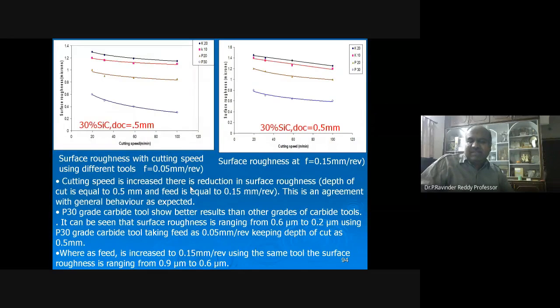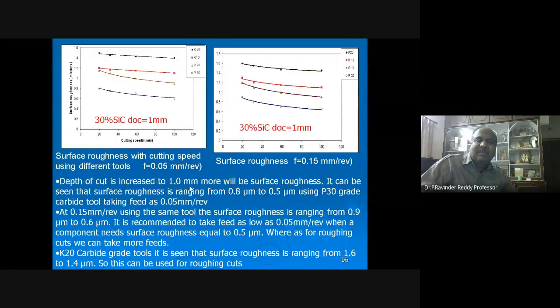So we have calculated at different feed rates, keeping feed rate constant and depth of cut constant; all the parameters have been studied. As the depth of cut is increased to 1 mm, the surface roughness will be higher. It can be seen that the surface roughness ranges from 0.8 microns to 0.5 microns using the P30 grade carbide tool. At 0.15 mm per revolution using the same tool, the surface roughness ranges from 0.9 microns to 0.6 microns.